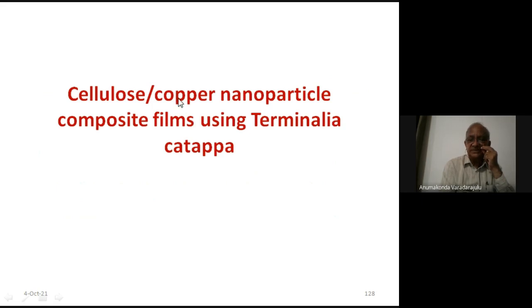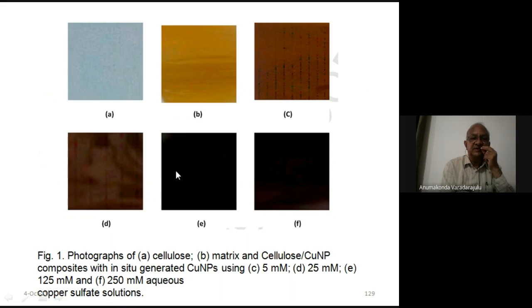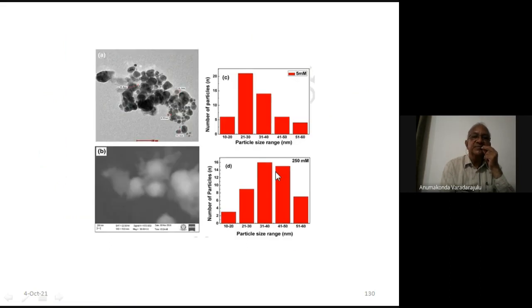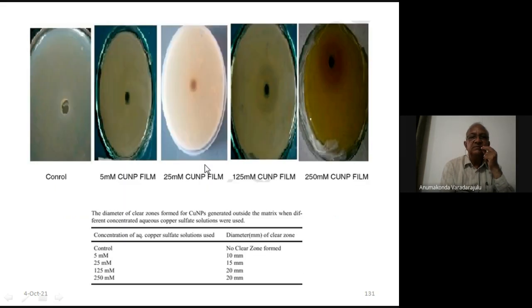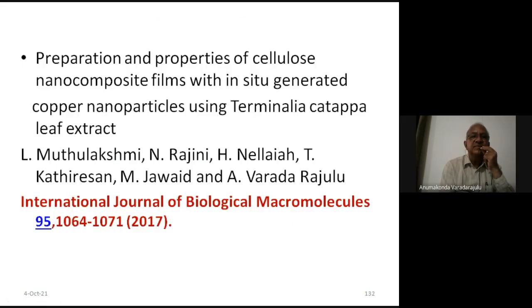Then we also generated copper nanoparticles using the same leaf extract of Terminalia catappa. This is a matrix and these are the composite films. This is a TEM. And these are the antibacterial zones. The zone diameter increased with increasing metal salt solution concentration here. So this can be used for antibacterial dressing materials as well as antibacterial packaging films.